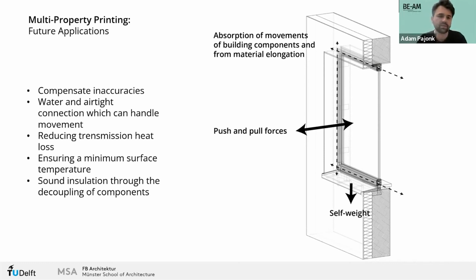In addition to this, the connection would also compensate for inaccuracies and create a water and airtight connection which can handle movements, as well as reduce transmission heat loss, ensure a minimum surface temperature, and provide sound insulation through the decoupling of the components itself. So the idea is to combine all of these functions in a 3D printed frame structure, which can ideally be directly applied on the construction site itself.